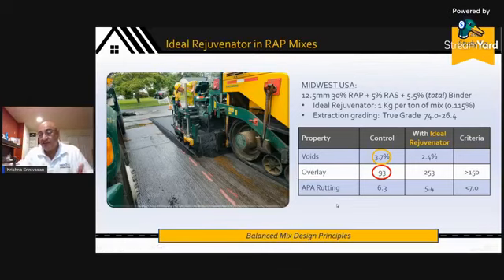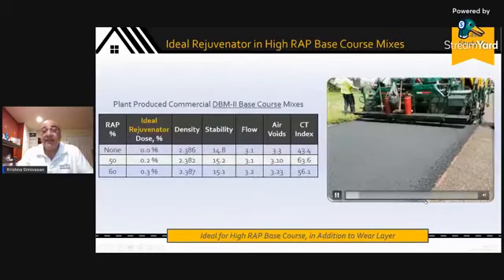Remember, we spoke about this balanced mix design. You're looking to trade off rutting versus fracture toughness. You can see we're failing the test criteria at this mix without any rejuvenator. But when you add the rejuvenator, you're able to get all these properties in balance. And that leads to a good mix.